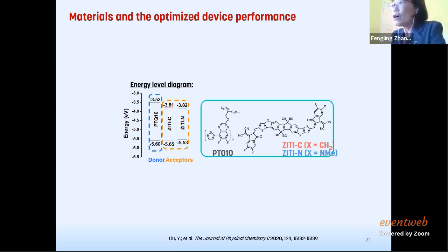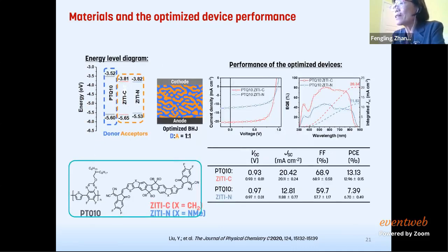It's very close in the orange part. One is 5.65, one is 5.53. For 5.65, there is still a little bit of driving force. But for this ZITI-N, there is almost no driving force at all, because it's a negative offset. So with these, we make the devices. This device at optimized bulk heterojunction means the ratio of donor and acceptor is optimized. It's 1:1. Then we get the performance as shown here.